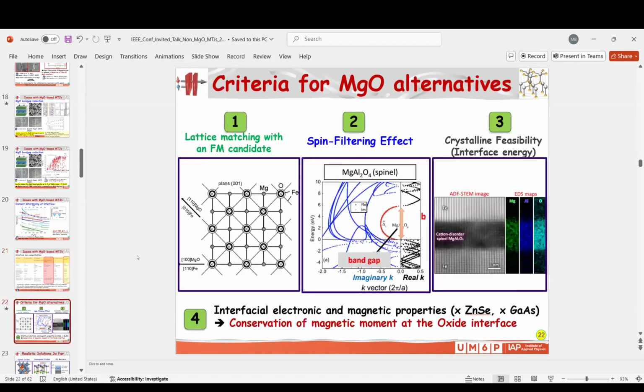So let me summarize here the criteria for an MgO alternative. It should possess a lattice matching with the ferromagnetic candidates. So if we change the barrier, we still have an area to choose the ferromagnet. The spin filtering effect, to avoid the Heuslers' crystalline feasibility. Rarely do we talk about this, because this concerns chemical aspects at the interface, and also we need to conserve the electronic and magnetic properties at the interface, which is not the case for zinc selenide and gallium arsenide.